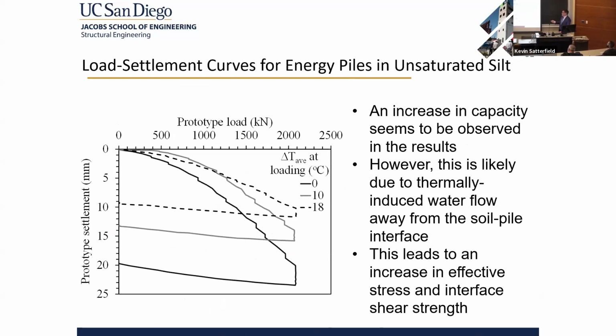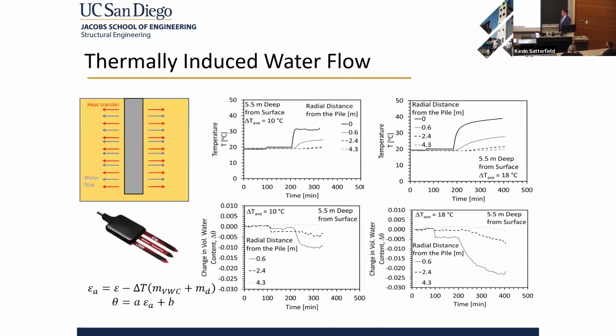Then we did the same thing on unsaturated silt. We saw that the hotter the soil was, the higher our capacity was. We attributed this to thermally induced water flow away from the pile, which led to an increase in effective stress and interface shear strength. And this was the case when we measured it using different sensors located at different locations from the pile. As the soil became hotter, it became drier.